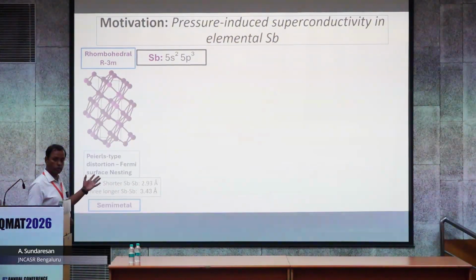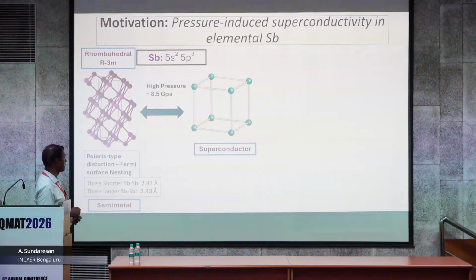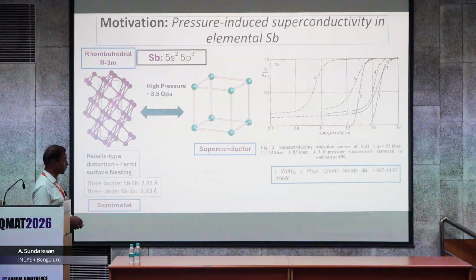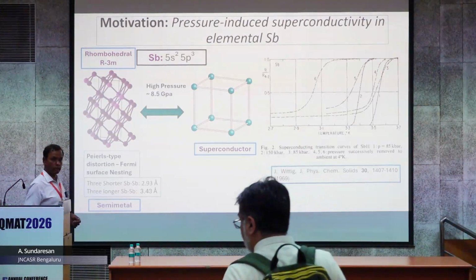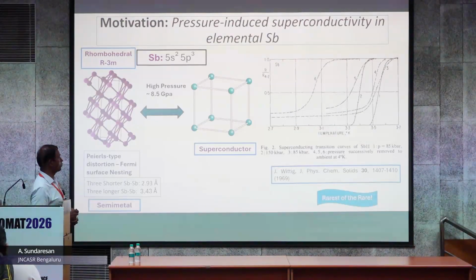This is what you see at ambient condition - the structure is rhombohedral, which is a semi-metal. There was a very old experiment where they applied pressure at room temperature, about 8.5 GPa. They didn't look at the structure carefully, so they thought it could be simple cubic, and they found superconductivity in this system when cooled to low temperature. These are the superconducting transitions at various pressures. Even when they removed pressure at low temperature, it was possible to retain a finite Tc, about 2 Kelvin or so. This was studied back in 1969.